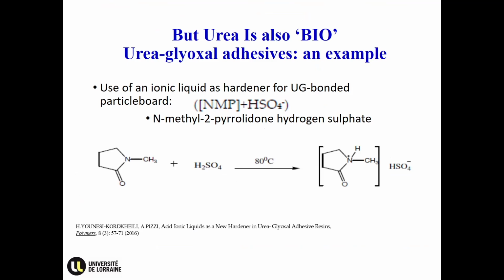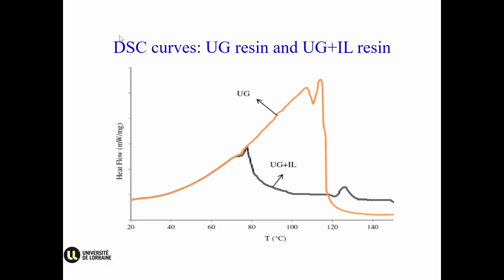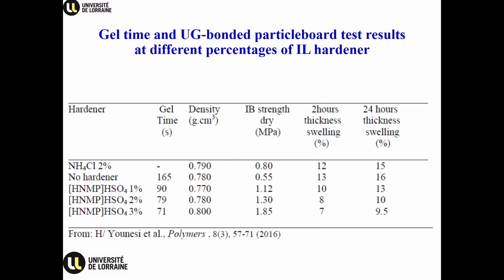If you use ionic liquids, you can have urea glyoxal reacting at the same speed as urea formaldehyde. The problem, again, is that sometimes with the ionic liquid, when it's homemade, the pH might be too low. Then you have to use a self-neutralizing system, as I showed you for soy citric acid. But soy citric acid or tannin citric acid alone are much, much easier systems than this. But you can use urea. You can see, for instance, by the DSC curve, the urea glyoxal resin and urea glyoxal plus ionic liquid. As you add the ionic liquid, the heat flow or the energy of activation is much lower, and hence you can have pressing times as fast as urea formaldehyde.